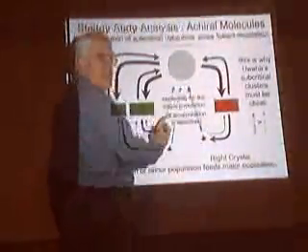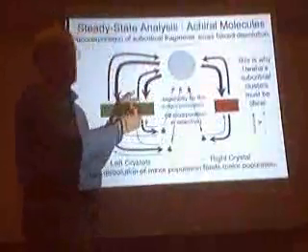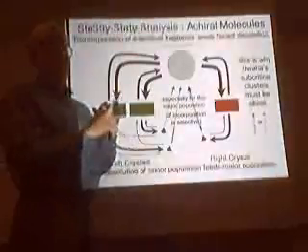Okay, now, let me go again. So in this case, the difference is that this is faster than either of these. So this one disproportionately feeds solution. But they come off from solution at the same rate. So that accomplishes a flow in this direction. So the minor goes to the major. And the only thing you need to assume is that incorporation is selective. A, that it occurs, and B, that it's selective. At least a little selective. And then you can argue about how selective it has to be.